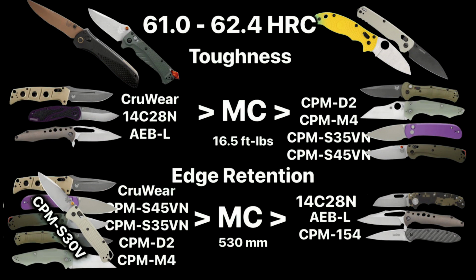We are now looking at the hardness range of 61 to 62.5 Rockwell. And as you can see, this range is even more densely populated than the previous chart by pretty well-known, very good steels. The big surprise here, for me at least, was that S30V has a much better edge retention than some of the steels that are considered more premium.